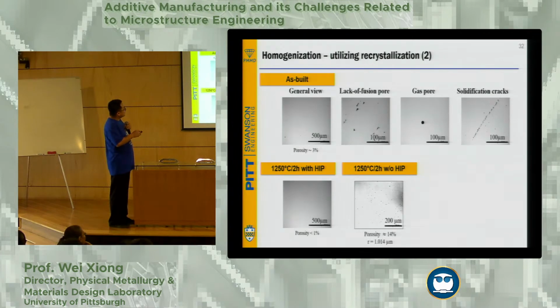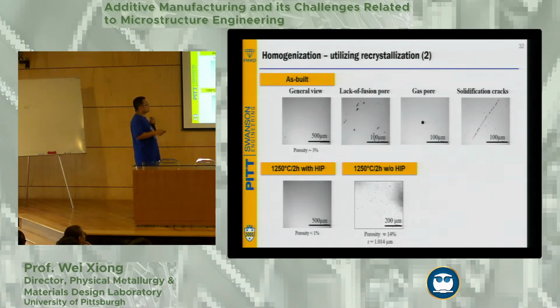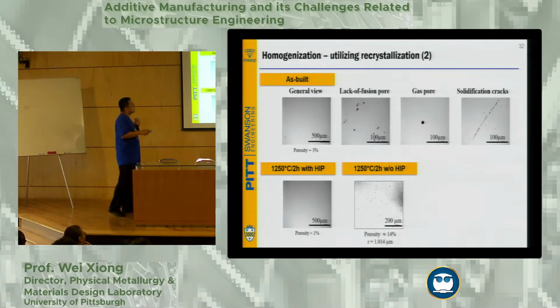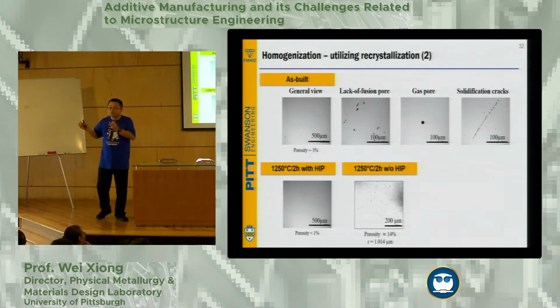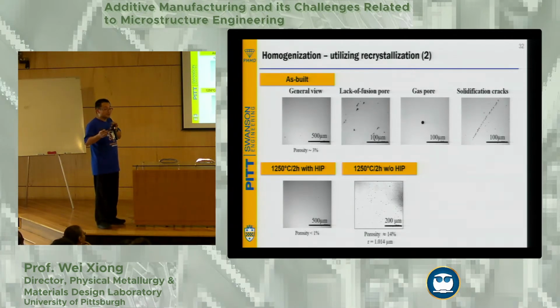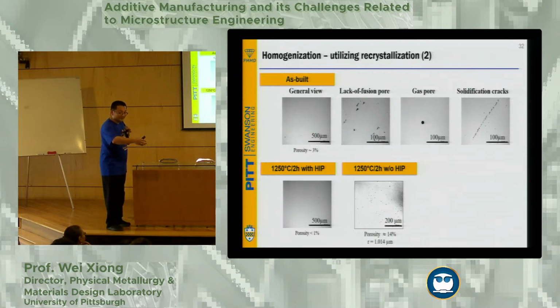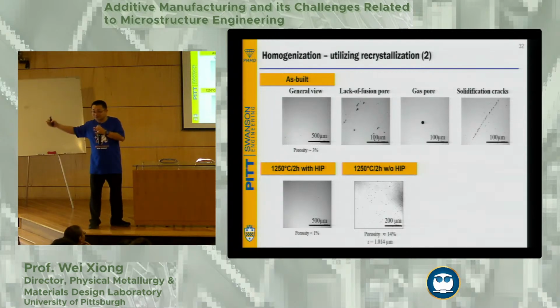So we actually find if you do higher temperature with recrystallization, then all of these pores become a problem. If you have the additive manufacturing introduced microstructure as here, you can see different pores. But then if you further do the homogenization, these pores will start to grow. That means you have to use another technique to solve the problem. So you get refined structure, but you introduce more pores, because the pores are actually growing.